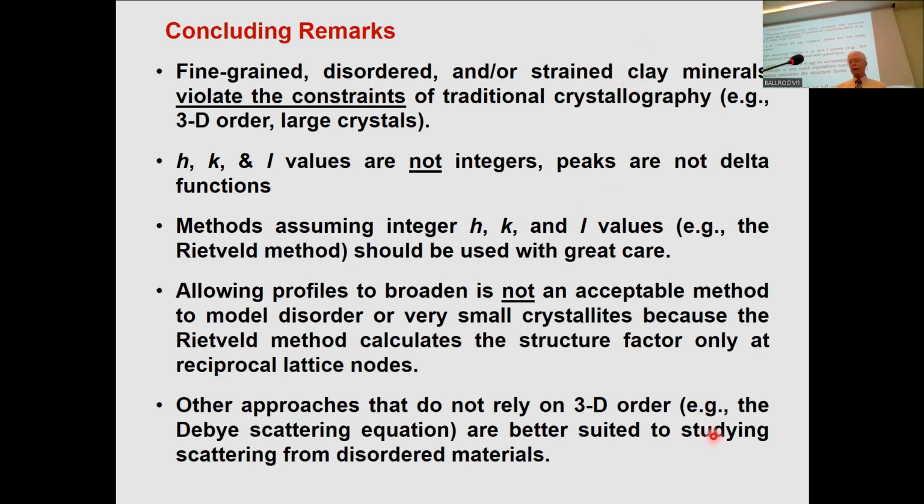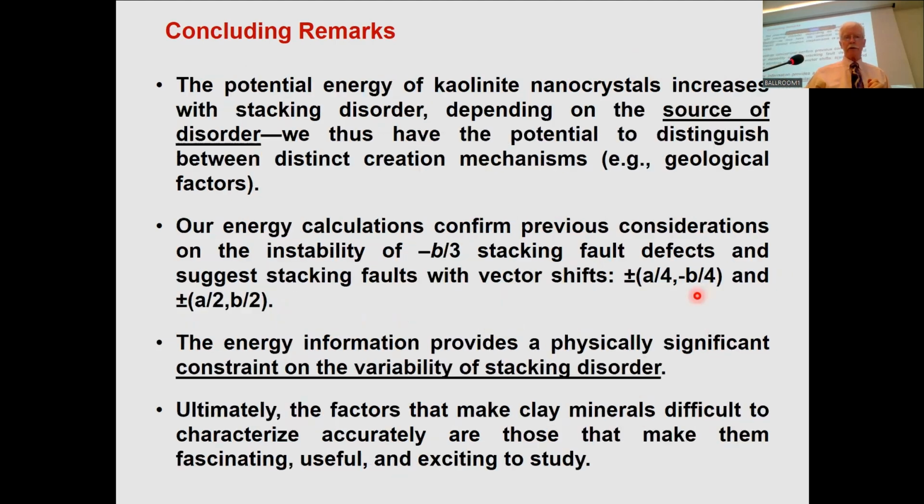And just remember, even if you can fit it, you can broaden the peaks. There are all kinds of ways with the Rietveld method to broaden peaks. The fact that you can fit it doesn't mean it means anything. Probably it doesn't. And using approaches like the Debye scattering equation, I think is the way to go in the future, particularly now that we have faster and faster computers. Probably in 10 years, there'll be young people in the audience who will be doing this routinely on their desktop. Right now, it's reasonably difficult.